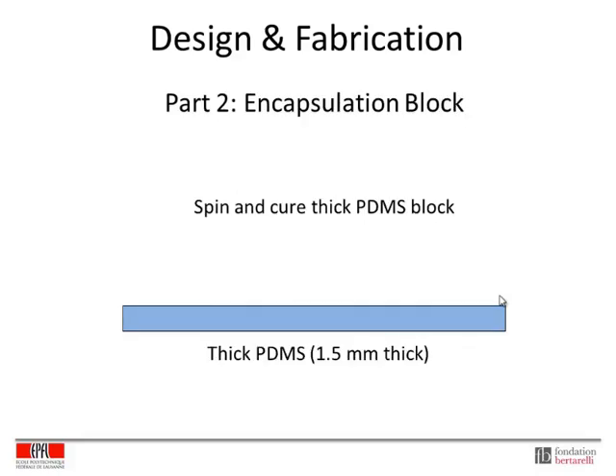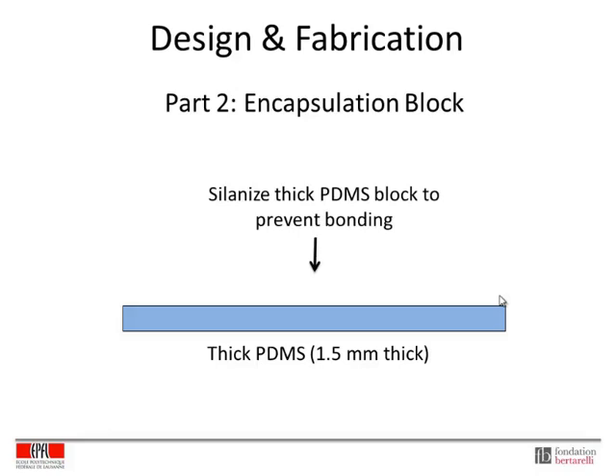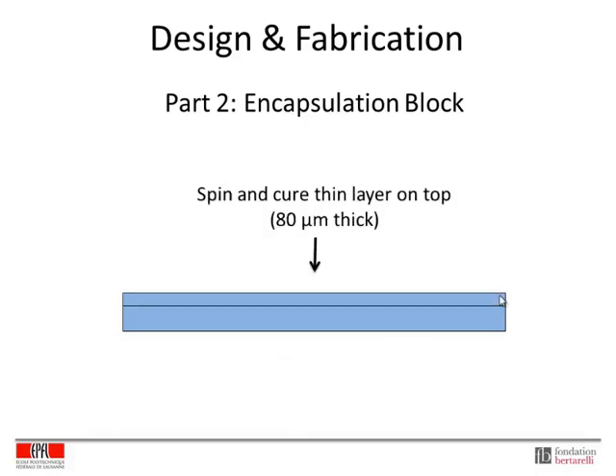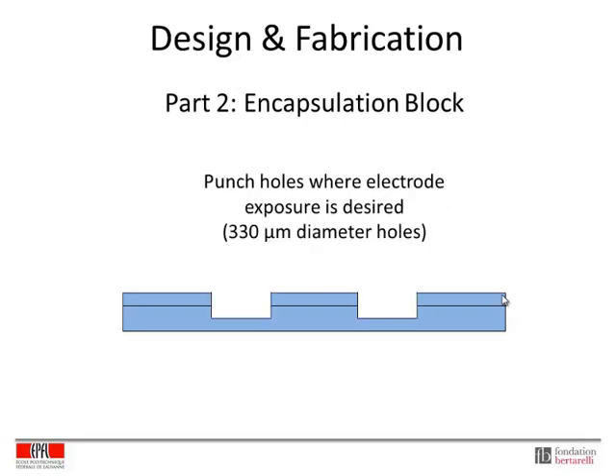Again, we spin and cure a thick PDMS block. This time it's much thicker than our substrate. It's about 1.5 millimeters thick. We silanize this block to prevent bonding, and the silanization will form a monolayer that gives the PDMS a non-stick surface, which is important for the next step. We spin and cure a thin layer on top. In this case, we wanted our encapsulation layer to be 80 microns thick, so that's the thickness that we used. Then we punch holes where we want our electrodes to be exposed, and the hole puncher has a diameter of about 330 microns.